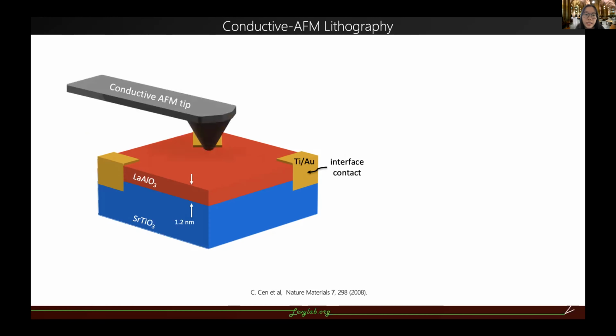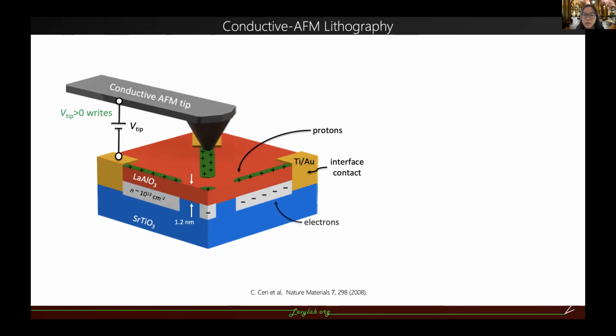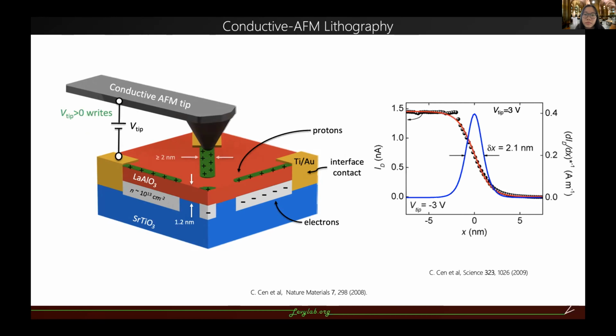When we apply a positive voltage to the AFM tip and drag it along the top surface, it will leave a path of protons. These paths of protons will act like a local top gate, tuning the interface below the path through metal-insulator transition. This writing process has a very high resolution. The width of the wire can be as small as 2 nanometers, and it's also reversible, which means we can simply erase it by applying a negative voltage to the tip and dragging it to erase the device.